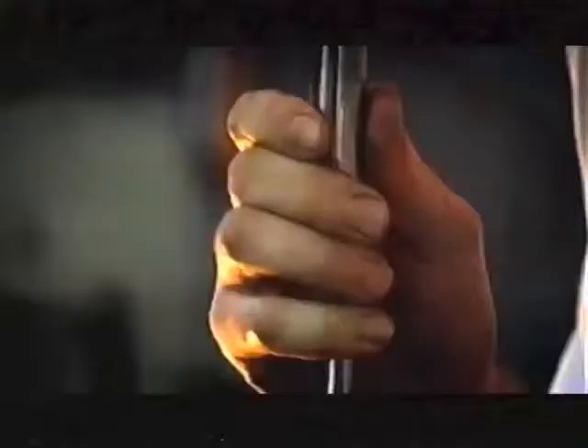When the glass is approximately the right shape, it's put into a wet mold. This creates a layer of steam between the glass and the mold, which gives the glass its smooth surface and cools it. The glass now has its basic shape and passes to the stem maker.